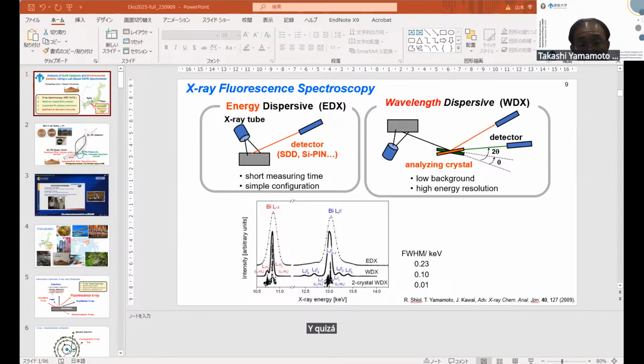The emitted X-ray is dispersed using analyzing crystals, changing the energies, and detected. By use of this one, it has low background and high energy resolution, and we can obtain a good spectrum. This is the typical spectrum. The top one is recorded in EDX style. Then this band width is maybe 200 eV. But with WDX, the width is narrower. By use of two crystals, we can record very high resolution spectra like this.